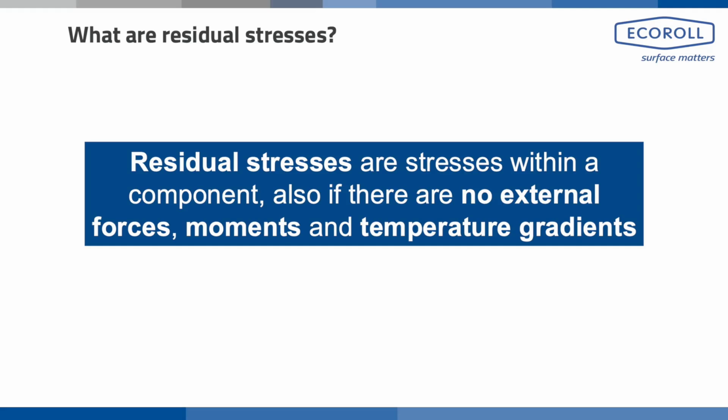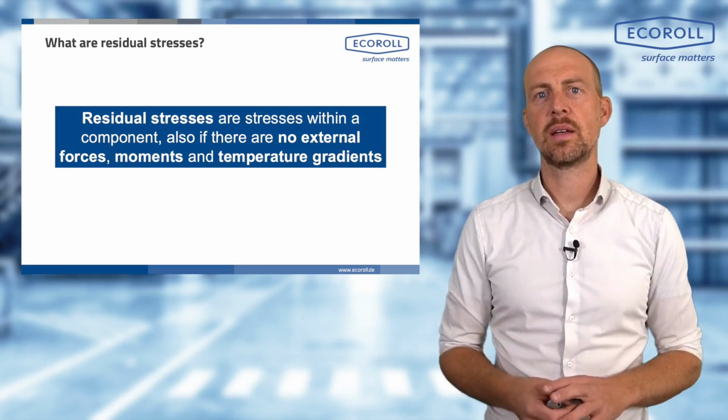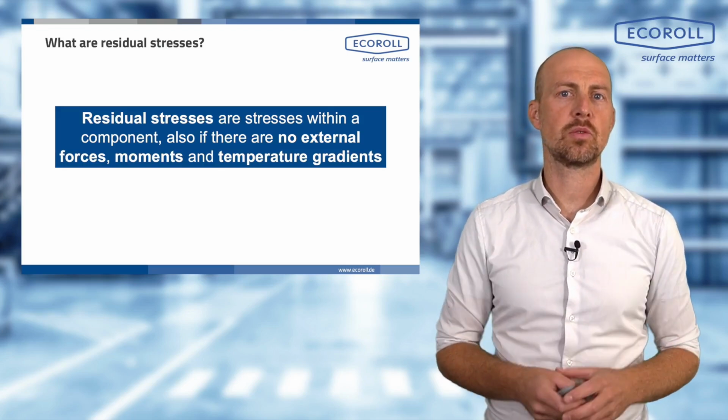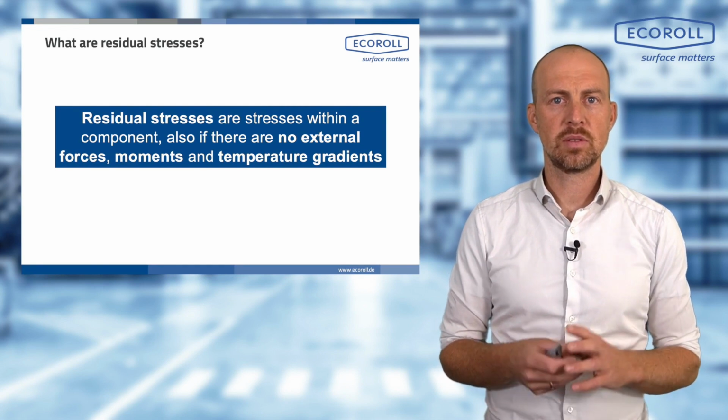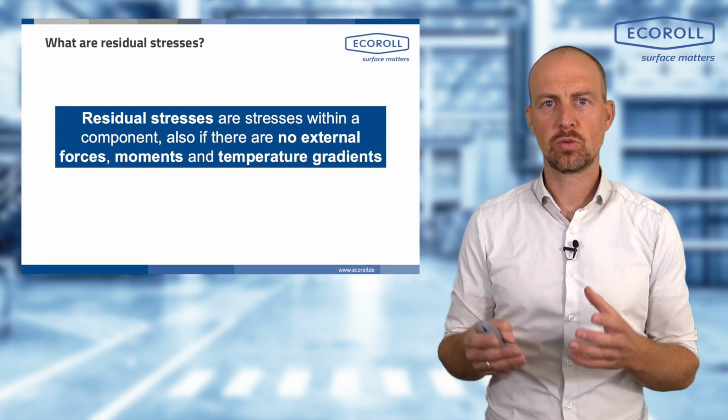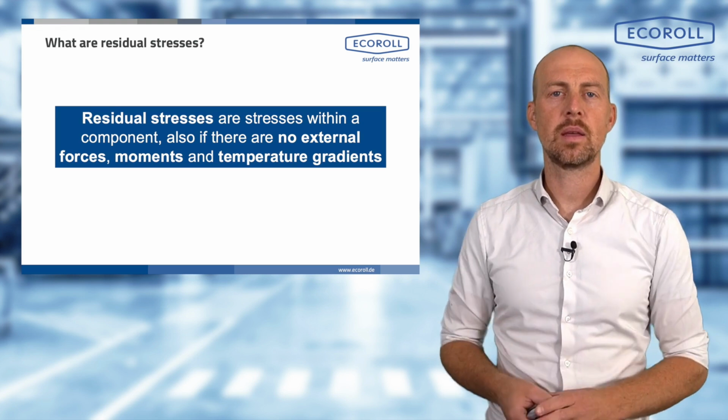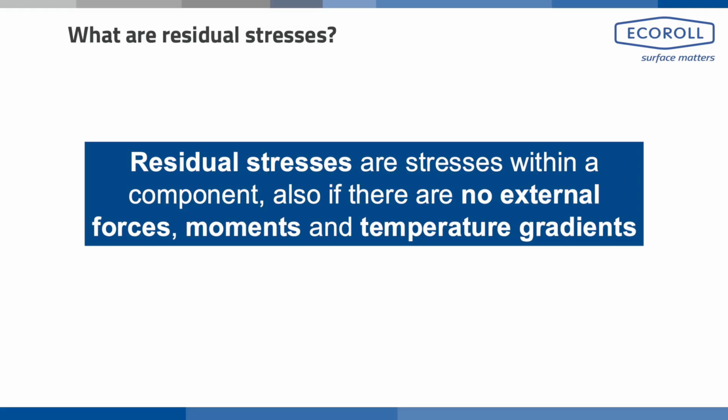Residual stresses are stresses within a component that exist even when no external forces, moments, or temperature gradients are applied. This means that a component still has residual stresses even when it's just lying here on the table in front of us. So if you have your shaft, your component, or your forming die lying here in front of you, there are residual stresses present in it. Residual stresses are introduced by every manufacturing process. Whether they are forming-induced residual stresses, machining-induced residual stresses, or stresses introduced by thermal or heat treatment, it doesn't matter.